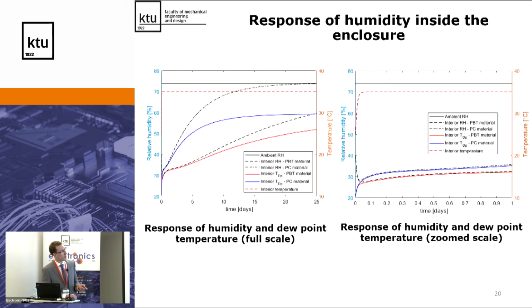So we have two processes. In the beginning, in the zoom scale, of course, the relative humidity drops because the temperature increases inside. Depending on the material, PBT has a lower diffusivity and solubility, so relative humidity drops more. In the case of polycarbonate we have a bit higher relative humidity, because due to its diffusion coefficient the moisture can flow faster through the wall.